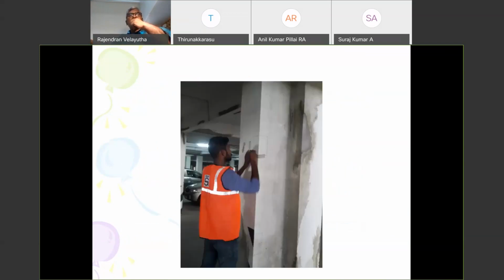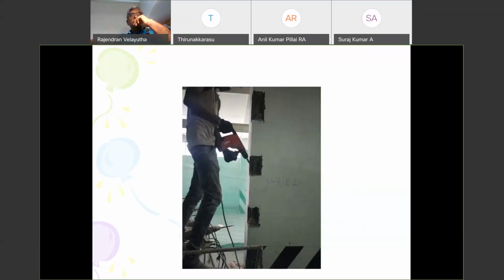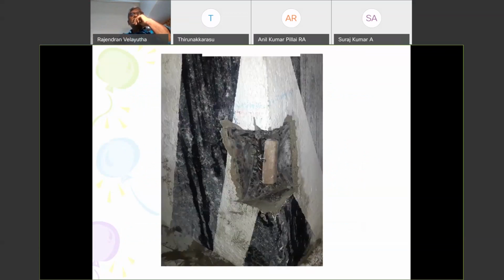So what is being done in practice is that anodes are being used in a simple system. I just wanted to throw some light on it. I'm not going to discuss in detail. So do the profometer survey, find out where the main rebars are. Just cut open the area where the rebars are exposed, and then tie this anode to the steel. In this anode, what you have got is a zinc inside, about 55 to 60 grams of zinc, depending upon the type of anode which you are going to use. And this anode is covered with a very high pH lithium matrix, which is going to act as an activator.